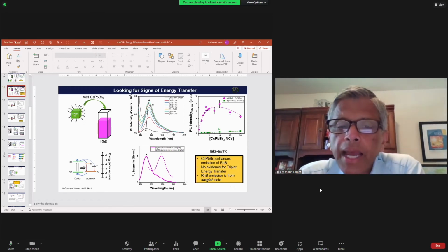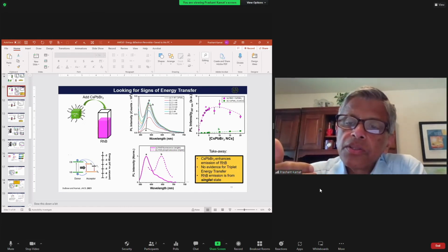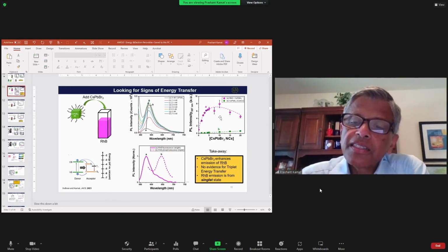Yeah, because there is an absorption thing involved, right? Once you pass the Beer-Lambert law regime, the absorption is not linear. Most of the absorption is near the closest surface to the cell, and it is not uniform. That's why you will start seeing a decrease at high concentration. This is not coming from the system. The linear region is only at low concentrations, when the absorption of the cesium lead bromide you add is linear.